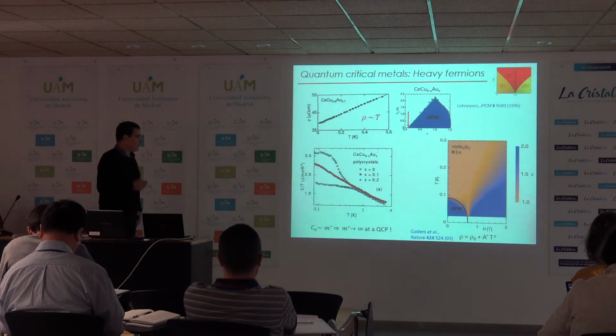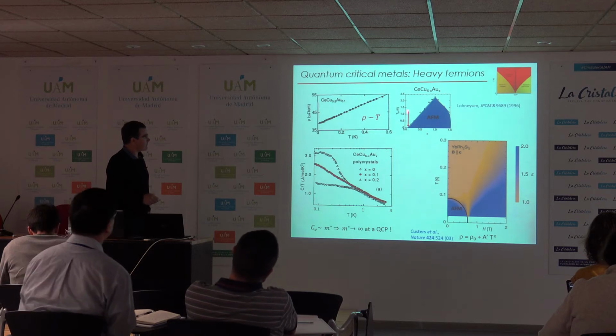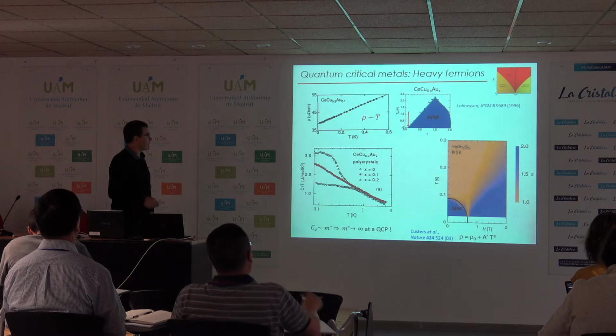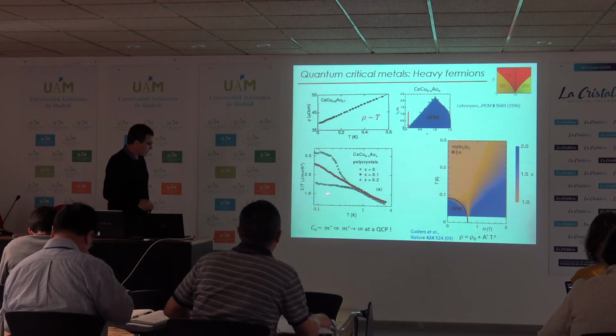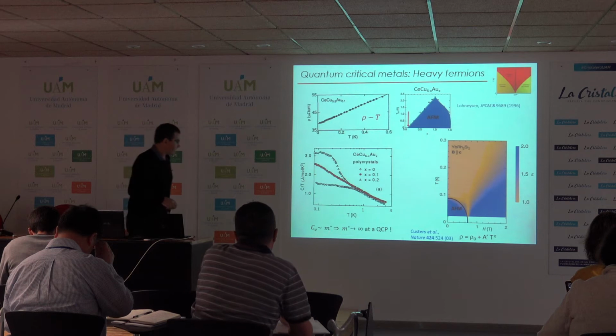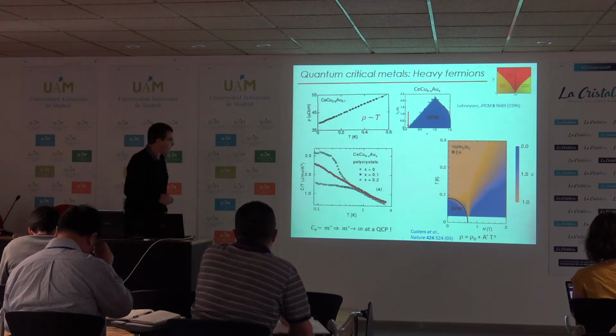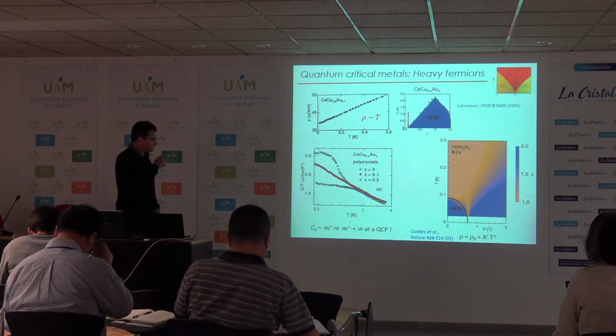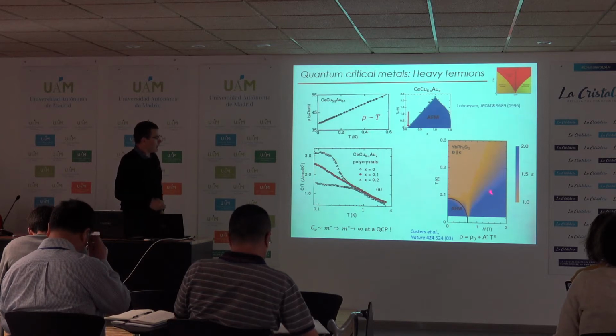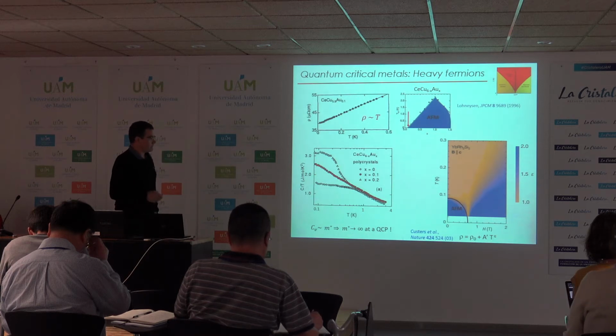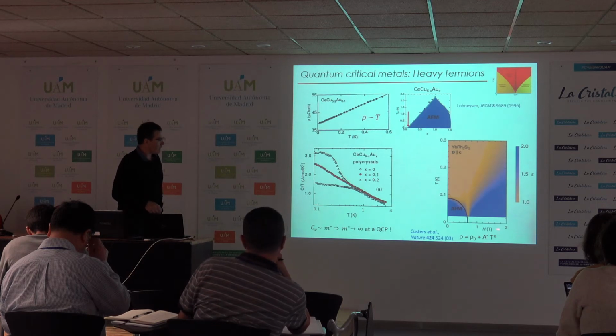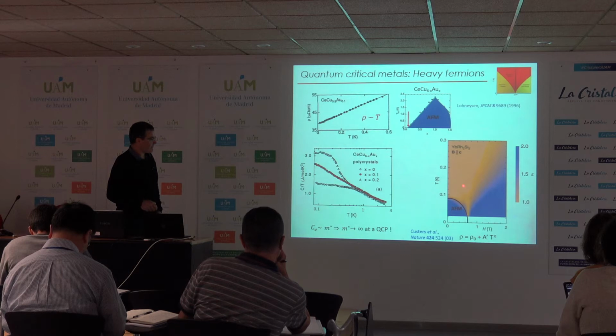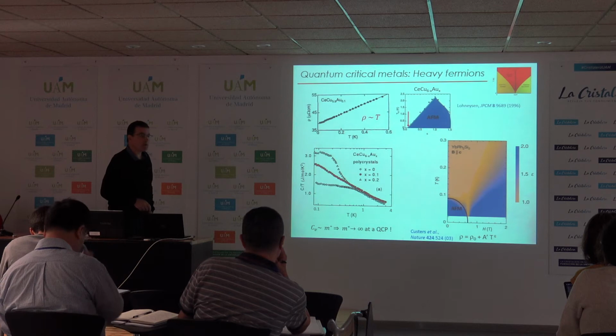If you now measure the specific heat in this compound, there is a linear term for the parent compound, but as soon as you add gold, at 10% gold, at the quantum critical point, the specific heat diverges logarithmically, so the scale is logarithmic. Since the specific heat is proportional to the density of states, this means that the effective mass seems to diverge at this quantum critical point. And here I show you an example of a map of the coefficient of the electrical resistivity, plotted as rho 0 plus coefficient times T to the power epsilon. Epsilon equals 2, meaning a Fermi liquid, when it's blue, and epsilon equals 1 in orange. And you see that this linear resistivity extends to T equals 0 only at the quantum critical point.